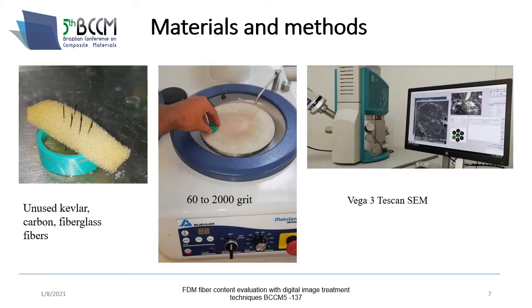The materials and methods employed were unused Kevlar, carbon, and fiberglass fibers. These were taken from the manufactured spool. They have a diameter of 0.4 millimeters. We take a bunch and then we perform a metallographic encapsulation with 60 to 2000 grit, and then we analyze them in a scanning electron microscope, Vega 3 Tescan.